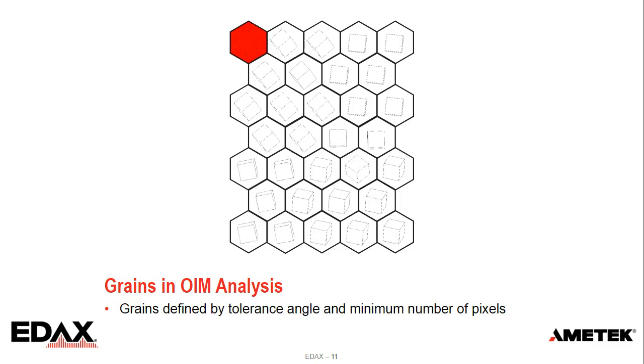So we start with our first point that has some orientation. The orientation is shown by a little unit cell, and we've colored it red. We check the next pixel. If the misorientation between that pixel is less than our tolerance, then we say it's within the same grain. And we repeat this process. We check this one. It's still within the same grain. And we check this one. It is not within the same grain.